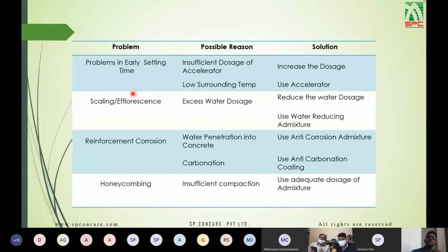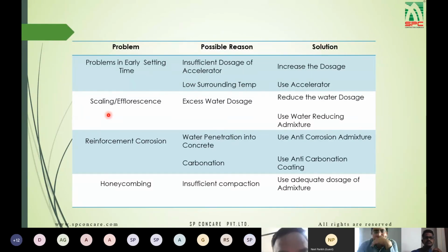Next problem is early setting time. Again, insufficient dosage of accelerator may cause this problem. So increase the dosage of the accelerator. Then again, due to the low surrounding temperature, this may also happen. So use the accelerator. The next problem is scaling or efflorescence on the surface of the concrete. Due to the excess water dosage, this may happen. So just reduce the water dosage and use the water reducing admixtures.